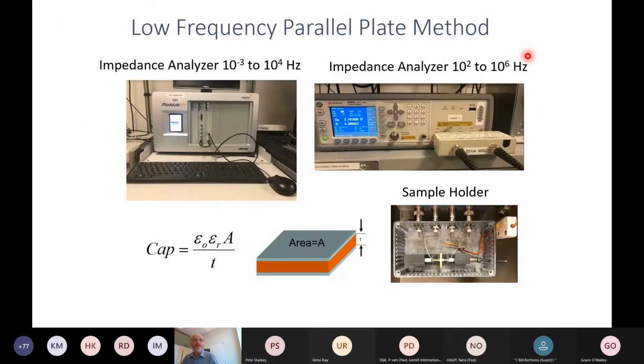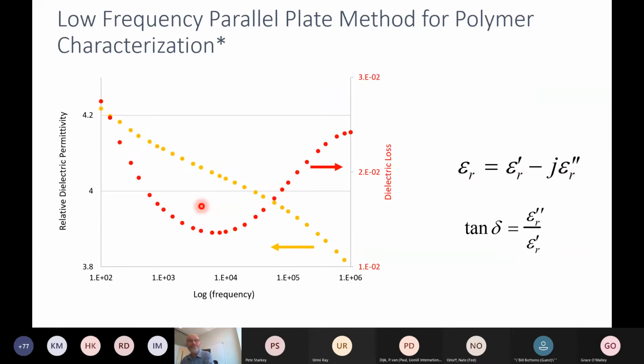So the first one, just a low frequency parallel plate. It's pretty standard. You have metallization on both sides of a dielectric, and then you can back out from the capacitance measured by these impedance analyzers. You can back out the permittivity if you know the dimensions, and that's certainly very useful for many orders of magnitude of characterization. Just an example shown here for our 3D printable polymers.